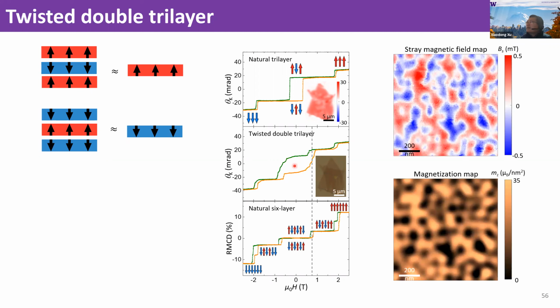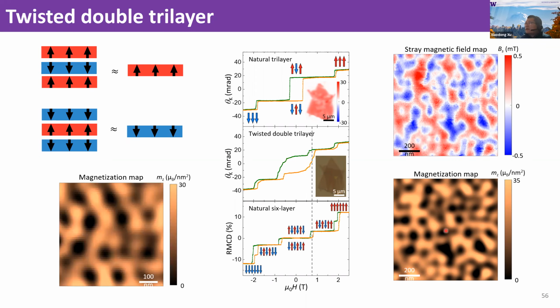Okay. So next, we perform the same single spin quantum magnetometry on this twisted trilayer on trilayer. The top is a stray magnetic field map, and the bottom is a magnetization map. Now you look at this, it's not as disordered as we see for twisted bilayer; you start to see some patterns. Of course, it's still a little bit disordered, but we can select some areas where, if you use a little imagination, it looks like some kind of hexagonal pattern there.